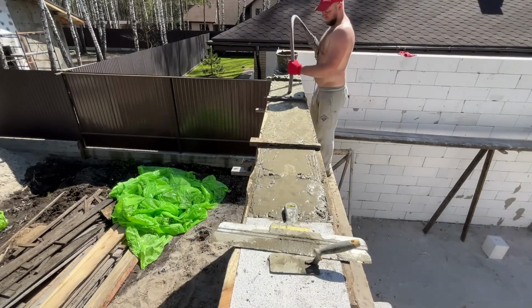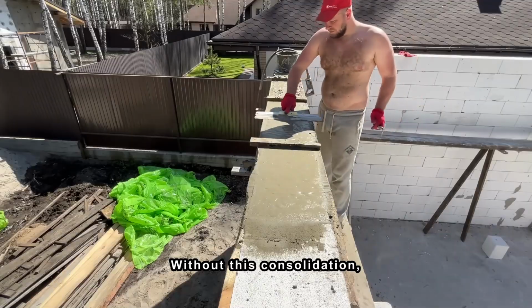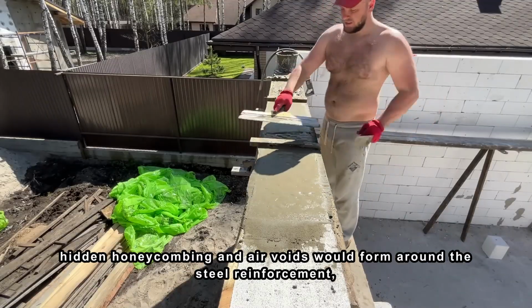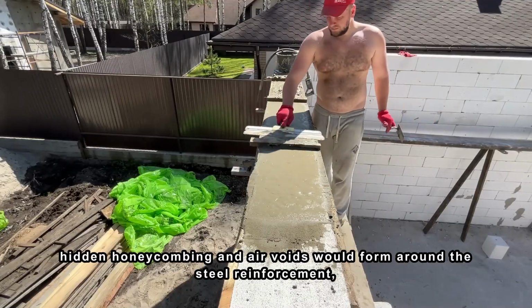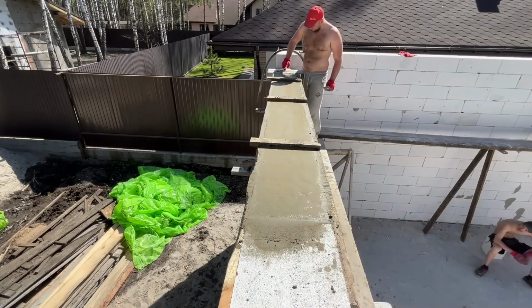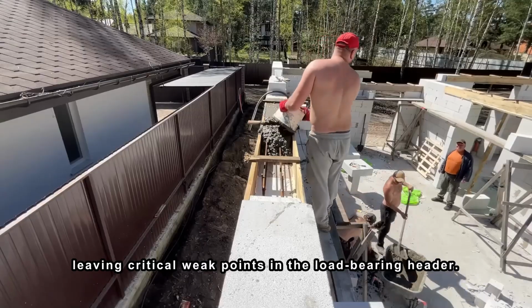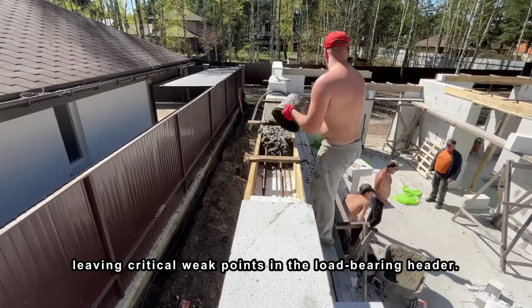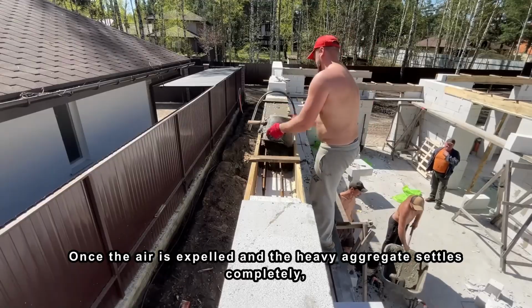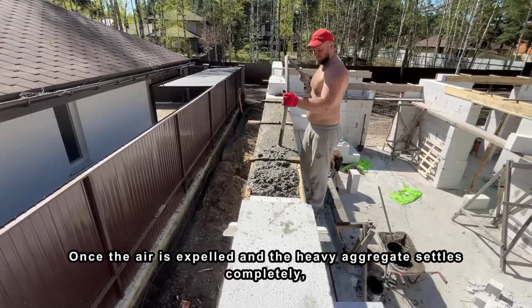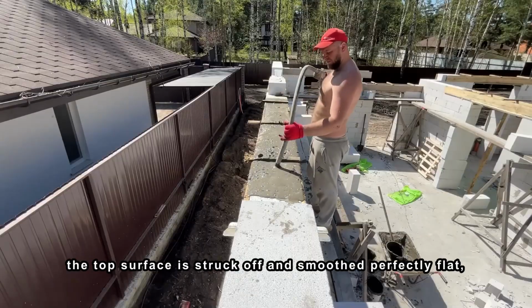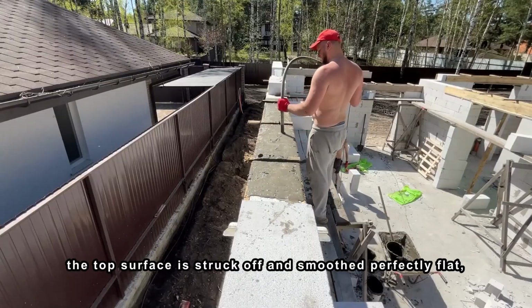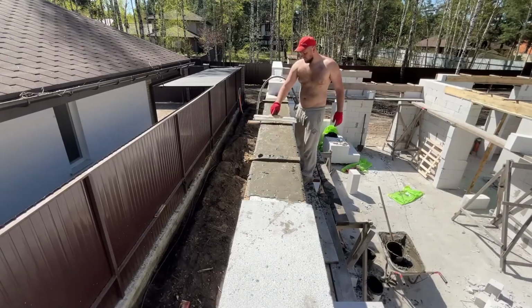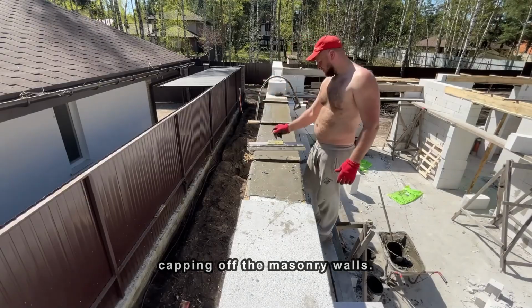Without this consolidation, hidden honeycombing and air voids would form around the steel reinforcement, leaving critical weak points in the load-bearing header. Once the air is expelled and the heavy aggregate settles completely, the top surface is struck off and smoothed perfectly flat, capping off the masonry walls.